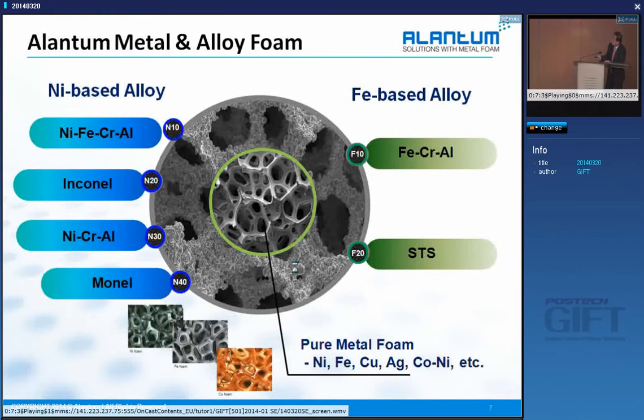But for the pure metal, in addition to the nickel and iron, we can produce copper, silver, or cobalt nickel. Cobalt nickel could be very, very popular in the fuel cell applications. So on top of this pure metal, then we can just spray or apply the powder, such as alloys. Then we can just sinter, making a homogenized alloy structure.